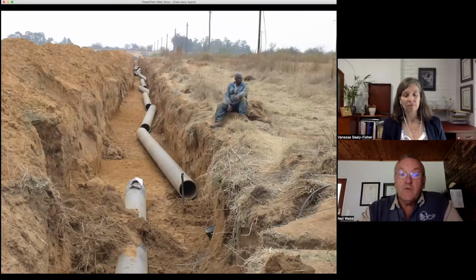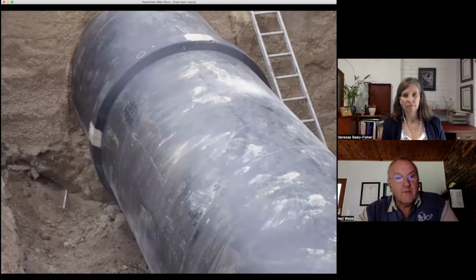And so when you put polyethylene onto a pipe, you are immediately faced with a challenge: how on earth do you get the polyethylene to stick to the pipe? And adhesion is one of the paramount characteristics that is important for a pipeline coating, and that is good adhesion, because we don't want corrosion to occur underneath the coating. And that brings us to the second limitation of polyethylene. Because polyethylene is so inert, it doesn't have particularly good underfilm creep resistance or inhibition of corrosion if and when the pipeline coating is damaged. In this photograph, we see a very good example of a large diameter pipeline that is coated with sintered polyethylene.